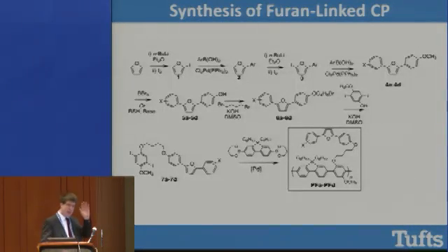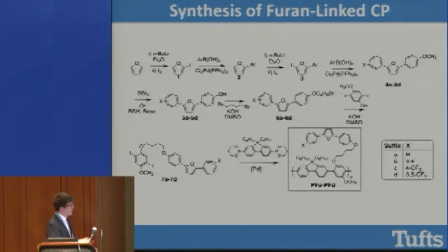And so we do a lot of organic synthesis in my lab. I'm not going to belabor this, but basically the design of this is that our fluorophore here is a conjugated backbone of this polymer. We made a number of these furan derivatives. And the singlet oxygen responsive moiety is this diaryl furan here. And so there's a number of derivatives that we made.